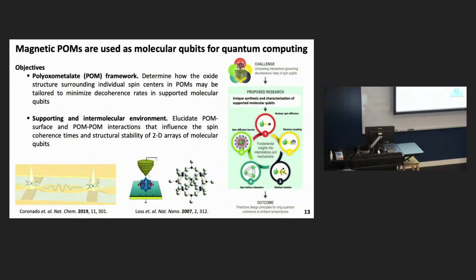In addition to energy storage, you can also use polyoxometalates potentially as molecular qubits for quantum computing applications. The idea here is you would dope the cluster with something like vanadium, which contains an unpaired electron spin, and then you would be able to create an array of these on a surface that would serve as a quantum gate. The issue is that it's not really understood how the oxide structure around those sites affects their decoherence rates, and it's also not understood how interactions between individual clusters and the surface affect their performance.